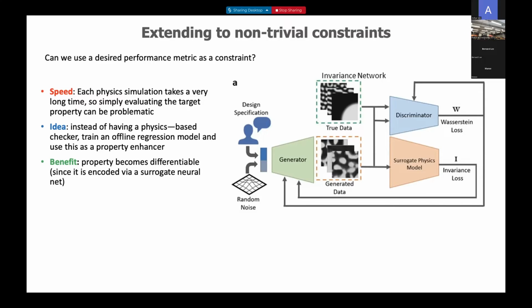Previously we showed that we can create grains or polycrystal matrices that satisfy a grain size distribution and grain orientation distribution. Now, given that information, if I can predict some microstructural property, we can essentially tune this. So if I say here's the property that I want, it's going to create a certain grain size distribution and grain orientation distribution that will get you that property.